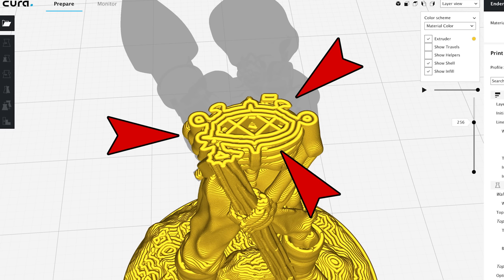You're not going to see the center of the mini, so nobody cares about that. The worst effects of the contraction are going to be the outer edges, and that is what you do see. Those are going to want to curl inwards and upwards. By having a miniature that is just outer shells with some space in the middle, like say 50% infill, you're giving more flex to those walls that they can better absorb those contraction forces without deforming as much. So you're going to get, again, a better looking miniature.